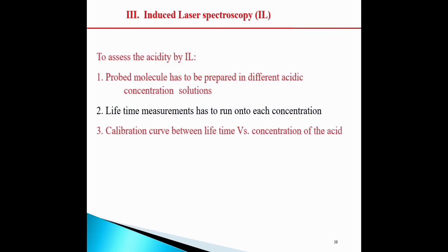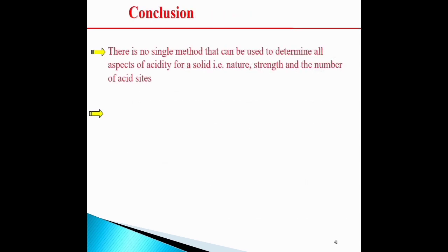In induced laser spectroscopy (IL), acidity is assessed by preparing the probe molecule in solutions of different acid concentrations. Lifetime measurements are run at each concentration to build a calibration curve of lifetime versus concentration of acid, using a laser spectroscopy diagram of lifetime in nanoseconds versus HCl concentration.